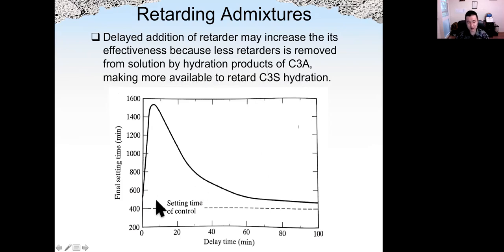So let's look at these figures. The x-axis shows us the delay time, which means how many minutes we delay after we mix the raw materials. We mix the cement with aggregate and with water. For example, here, this is a 10 minute delay of retarder. The final setting time will be much higher compared to 0 minutes delay.